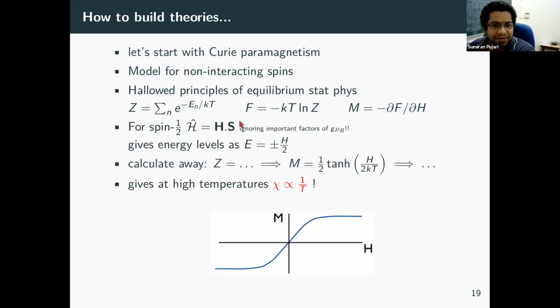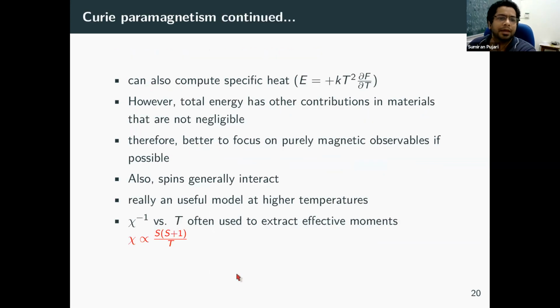For a spin half in a magnetic field, spin half, remember, has only 2 states, up and down. You can work out the eigenenergies. It's simple. You can calculate the partition function, free energy, magnetization, and thereby susceptibility. And you can actually arrive at the result of Curie 1/T behavior that I had sketched a few slides ago. So this simple model of non-interacting spins naturally gives you paramagnetic susceptibility behavior of 1/T. You can compute other things with this simple model, for example, specific heat and so on.